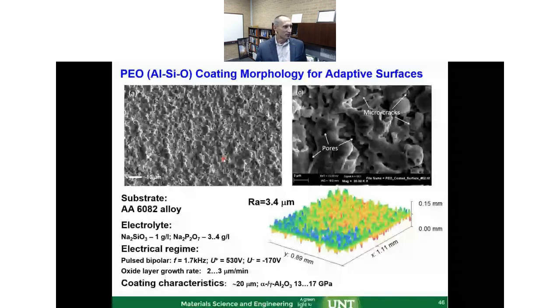But meanwhile, let me move on. In our case, we're using this highly porous morphology, so we specifically tune the process to open these pores, so we can use them as reservoirs for adaptive lubricant. Those electrolytes and regimes for making the coatings result in a well-developed roughness, and a coating again made out of alpha and gamma alumina, with also some silicates in there.